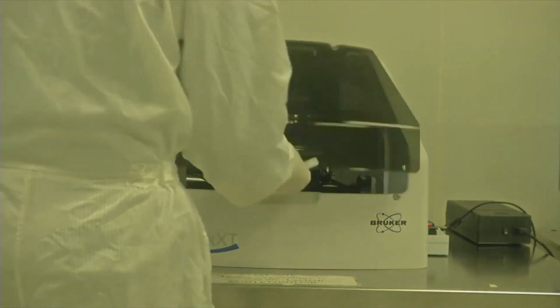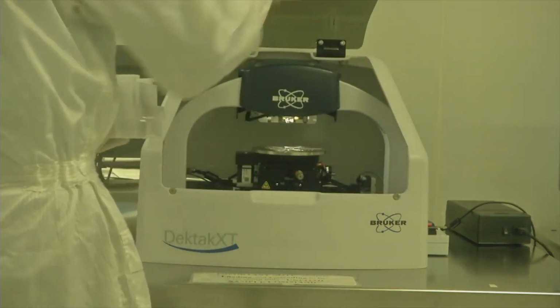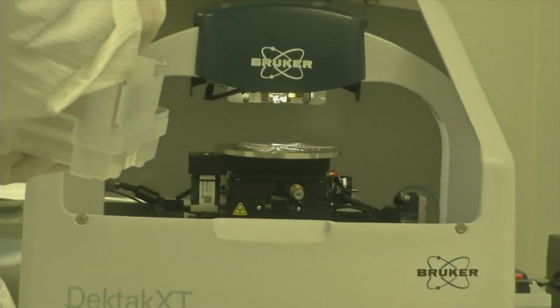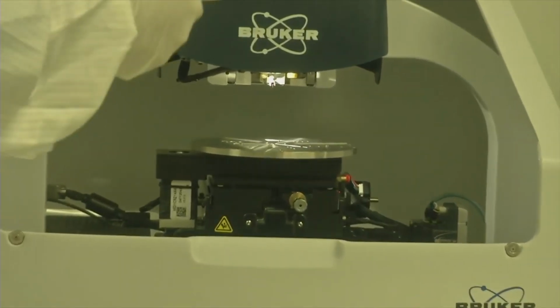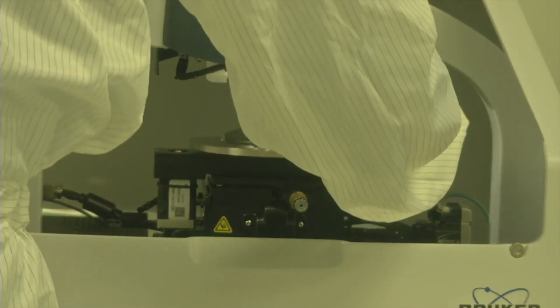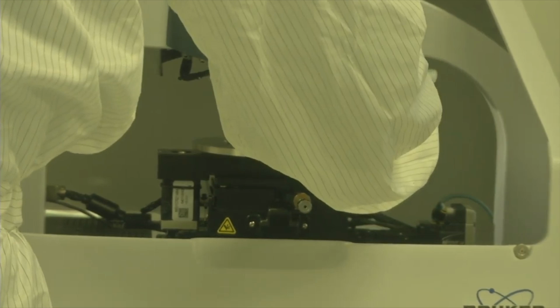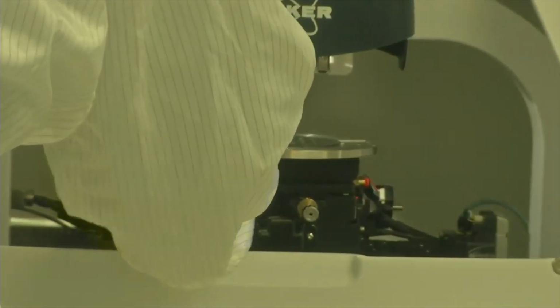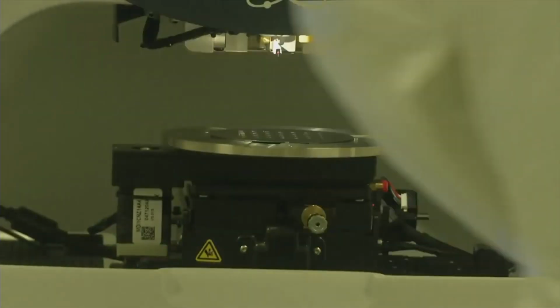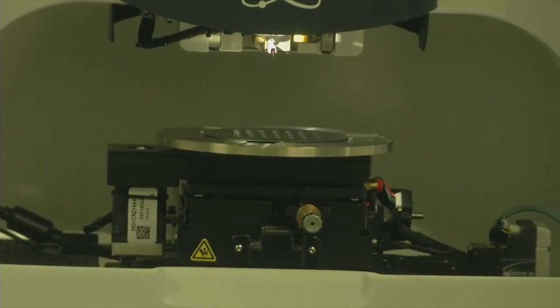And we are also going to measure the step height, right? We only saw from top down how the image looked, and now we are going to do step height. Because we have etched the film and also created an under etch, you expect a large step height difference in the wafer. So we are putting it for step height measurement.